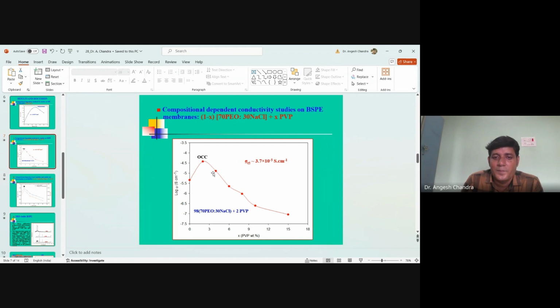polymer electrolytes. This figure shows the compositional dependence study of blended solid polymer electrolytes. This is the host salt, and this is the other polymer, polyvinyl pyrrolidone (PVP). And we can see here that as the concentration is increased, at 2 weight percent of PVP, the conductivity is maximum, with an ionic conductivity of 3.7 into 10 to the power minus 5 Siemens per centimeter, and a two order conductivity enhancement was observed at this particular composition, and this composition is known as the optimum conducting composition. Further increasing the concentration of PVP, the conductivity decreases.